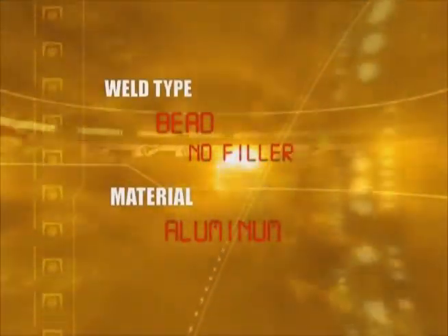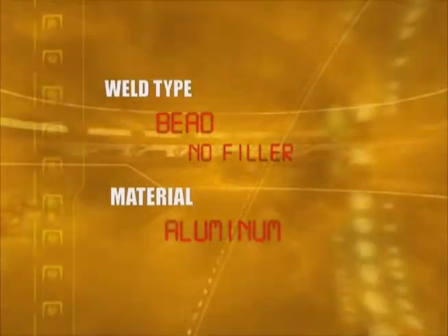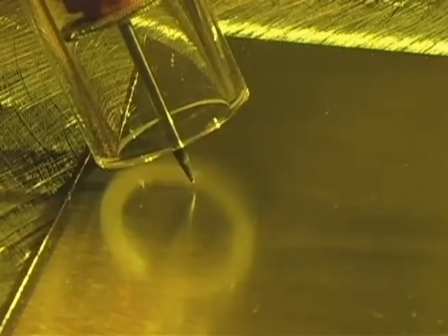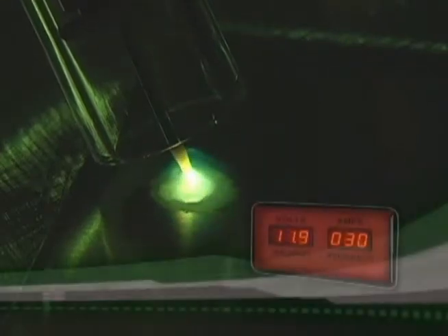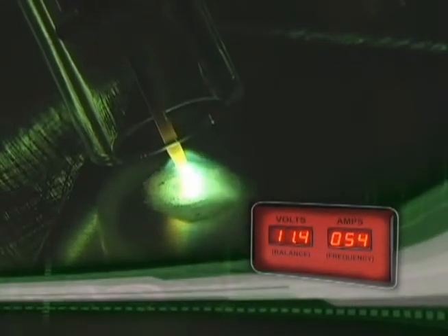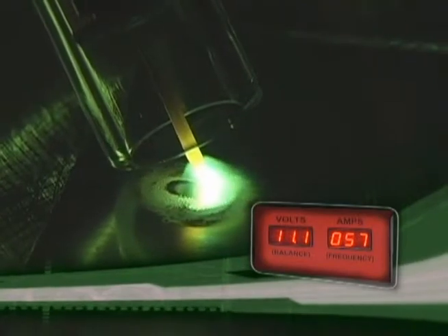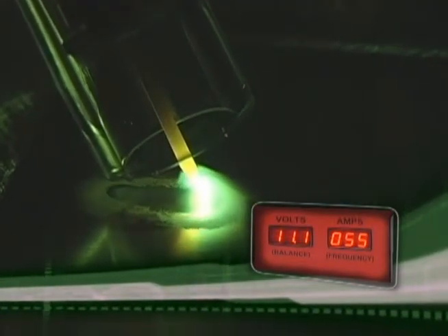The process for welding aluminum is very similar to steel. Once again, you are going to need to lay down a bead without any filler metal to start. You are trying to move the torch at a constant speed to give you a constant bead width, while keeping the tungsten between 1/8 and 3/16 of an inch off the work.